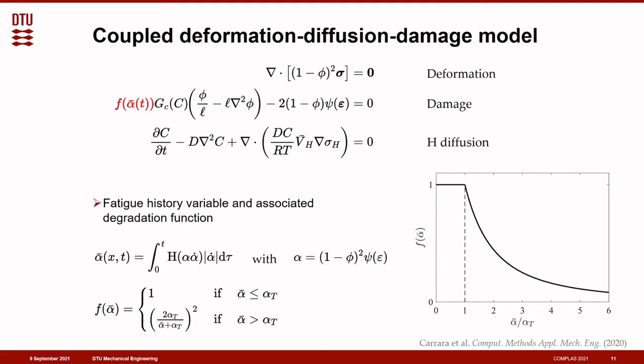which is also degraded by the phase field damage variable. Note that the accumulation of this fatigue history variable only takes place during the loading stage and not unloading. And for values below the fatigue threshold controlling parameter, alpha t, the fracture energy remains unaffected by fatigue.